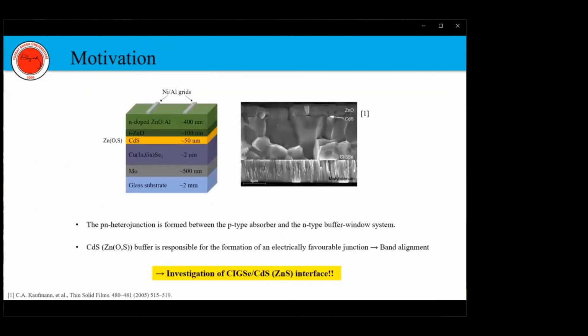Let me first briefly explain what a CIGS-based thin film solar cell looks like. The CIGS absorber film is usually deposited onto a molybdenum back contact using physical vapor deposition with a thickness of about 2 micrometers. The PN junction is formed between the P-type absorber and the N-type buffer window system. The cadmium sulfide, or alternatively zinc oxysulfide buffer, is responsible for the formation of an electrically favorable junction in terms of band alignment at the interface. Therefore, the main motivation of this work is the investigation of the CIGS buffer interface.